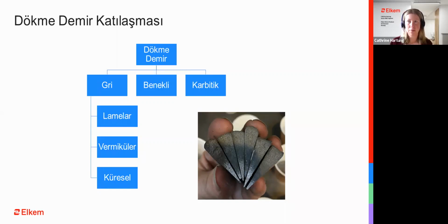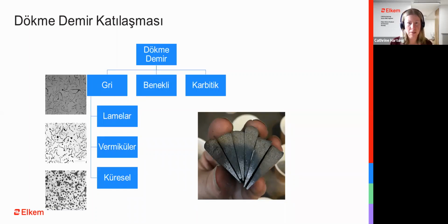So you see the chill wedge here. Next again, press next again. Here are the different types of cast iron that we have, where graphite is growing differently. It's either lamellar, compacted graphite, or the nodular structure. The chill wedges are easy to use for gray iron and partly for vermicular. For ductile iron, you need to cut and polish them to see the same structure as you see here. Next slide.